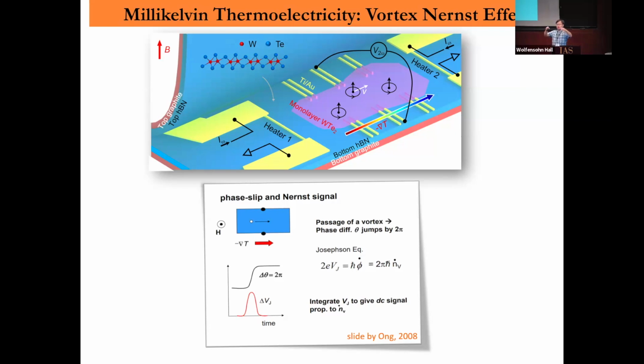In a superconducting condensate, they don't have entropy, it's a quantum condensate. But a vortex means you have normal electrons there, and any normal electron has entropy. So when you have a temperature gradient, it will follow that, because you're driving the entropy toward lower temperature. So when you have this vortex move, then you will pick up a phase difference as a function of time, like this.